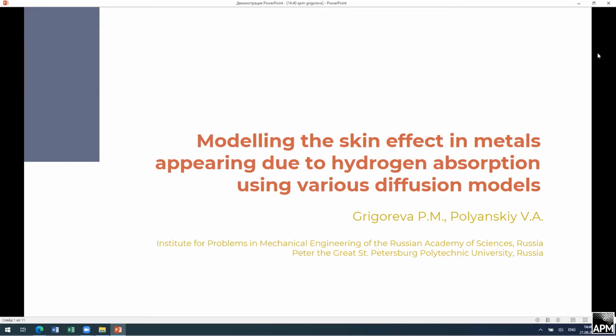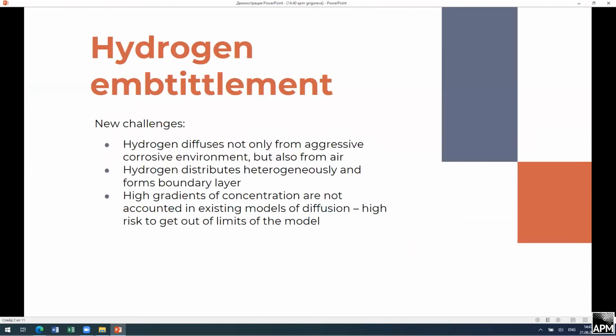So I'm going to make a presentation, probably in continuation of Ksenia's presentation, on how to model the skin effect in metals using diffusion models, not some models of behavior of material. So again, just to remind you what the new challenges in the diffusion problem are. The one thing is that the existing models of hydrogen diffusion prescribe the diffusion from the aggressive corrosive environment. But recent experiments show that hydrogen diffuses also from the air, from not high concentrations of the hydrogen.